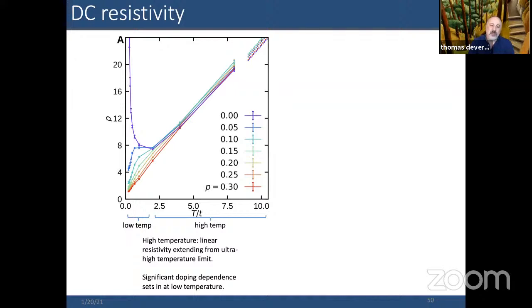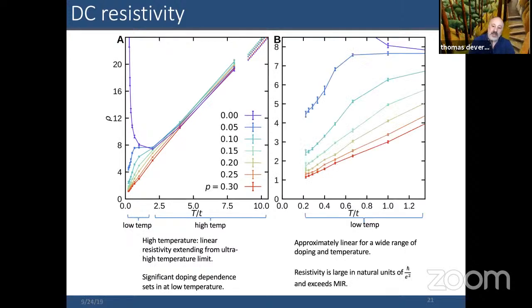But what is remarkable is the fact that there really is no dramatic change in temperature dependence going down to low temperatures from the high temperature behavior, as long as one gets away from half filling. So if we blow that up on the right-hand side, over a very large temperature regime, you see that the resistivity goes roughly linear. And of course, this is plotted in natural units of h bar over e squared. So all of these values are exceeding the Mott-Ioffe limit.